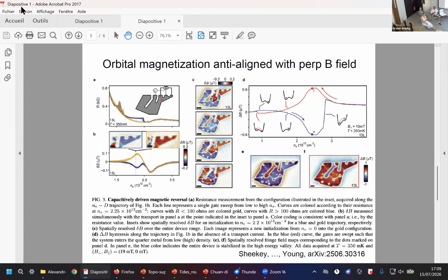And also they observe some edge states at step edges. So there is a clear signature of spontaneous chirality, so probably d-wave, d plus id. It's difficult to prove, but chiral for sure. So it means that we have at least one system which is super clean, with a fully open, hard gap, with a very high TC that could be of interest.